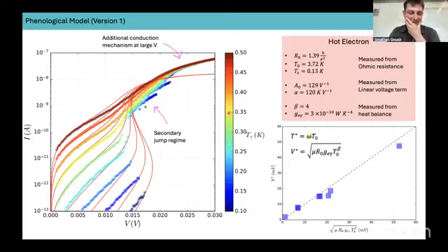Yeah, absolutely. This was one of the biggest challenges for the first couple of years of my PhD because these samples are so resistive. They can be gigaohms or even slightly higher. At very high resistances, you're very limited in what measurement circuit you can do. For example, the capacitive part of your circuit becomes comparable with your measured signal. This rules out AC, which scales with your driving frequency. So the main way of doing this is with a two-terminal DC measurement.